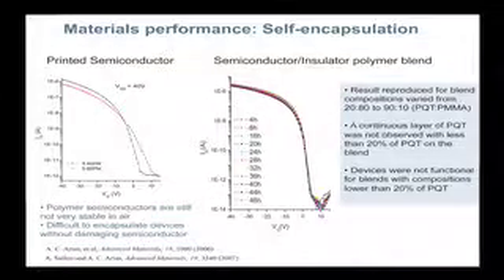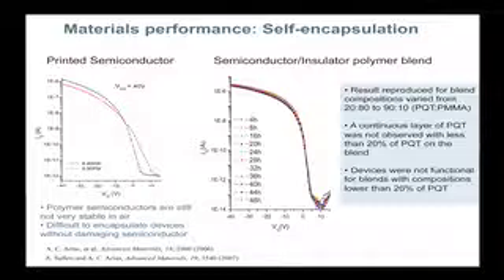So what happened then? You can see here that from a device that just in a few hours was moving over, the off current was not so good, the subthreshold slope was really suffering with a few hours exposed in air. You get something that is very stable in air for many hours, and it works even better than what you had when you only had one material there.